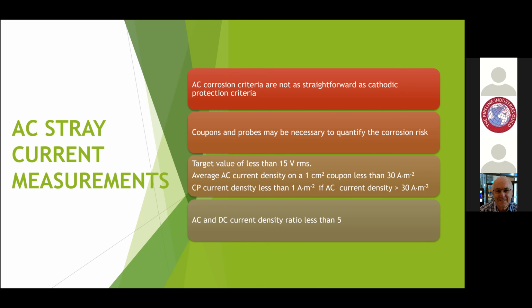And then finally, you can look at the AC and DC current density ratios on the 1 centimeter coupon, and they should be significantly less than 5. So this makes it difficult for anyone other than a specialist to determine which criterion is correct. But I'll explain later on that there is a way around this.